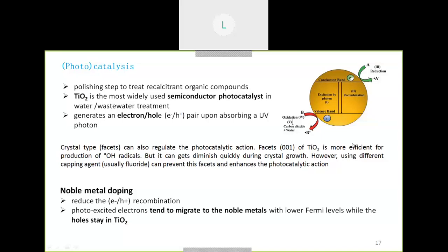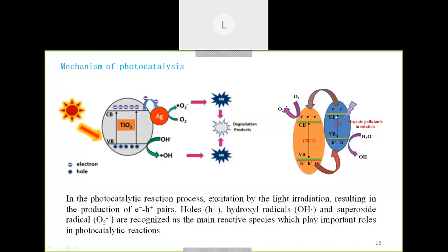So the electrons jump to the CB and then to the conduction band of the metal, where superoxide radicals are formed, which are able to degrade methylene blue, which is again an organic dye, into lower components. Another mechanism can also be given, where people have shown this: the electron from the CB of the conducting material jumps to the lower CB of TiO2, because it is situated at a lower position, and the holes present in the VB of TiO2 jump to the VB of the conducting material, where the separation is maintained. Again, you can get ROS, which is used for organic pollutant degradation.